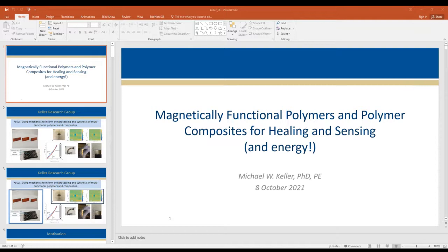The thermal sensing, to be fully honest, probably doesn't have much practical aspect, but it was a fun can-we-do-it type of thing. So we used induction heating to heat the contrast agent, so it's just locally heated. What we found is the nanoparticles are really small, and there's not a lot of mass there, so the switching frequency has to be super high in the induction heating. Induction heating works by alternating the magnetic field direction back and forth, and you get Joule heating or frictional heating. We had to have something like greater than 400 kilohertz, and we actually had to push it to nearly a megahertz of switching. That's something you can't buy commercially.